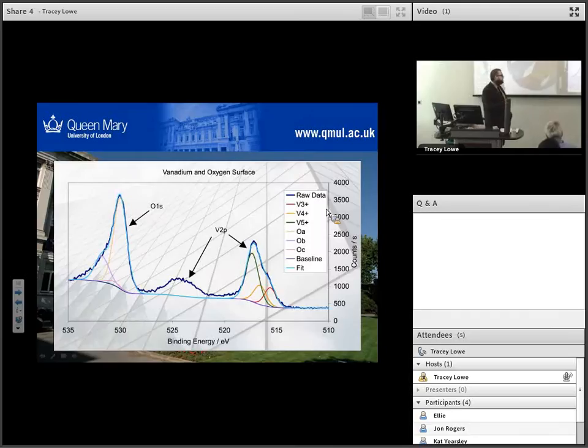However, if we do some XPS, we can see that we've got multiple vanadium environments at the surface, and indeed corresponding oxygen environments. If you do some etching, this tends to tidy up into a single peak. So the bulk of our material is vanadium dioxide.